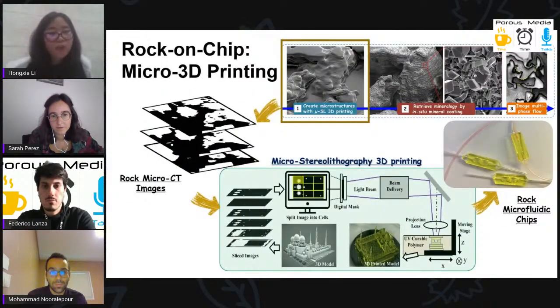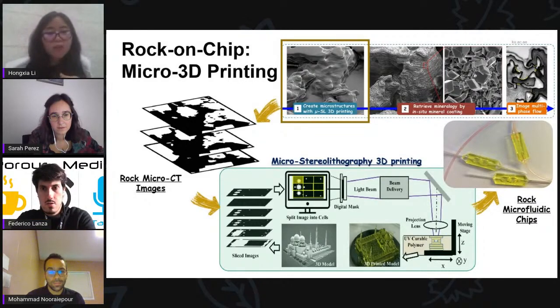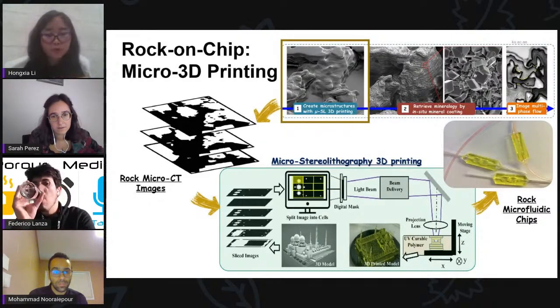That is how we can use 3D printing, starting from the micro-CT image of the rock. We use a so-called micro stereolithography 3D printing system. That system can help us print pores of 2 micrometer size. This is a light-based 3D printing method. After printing, we can see the microfluidic chip is actually transparent, so it can facilitate our imaging purpose.